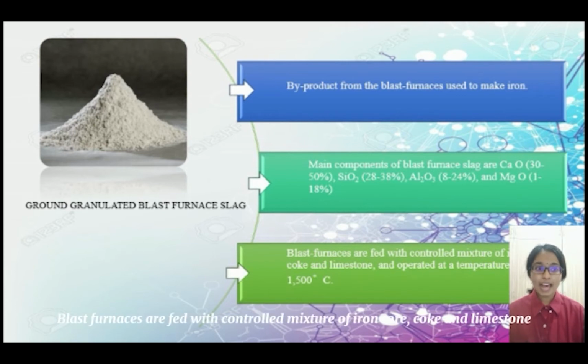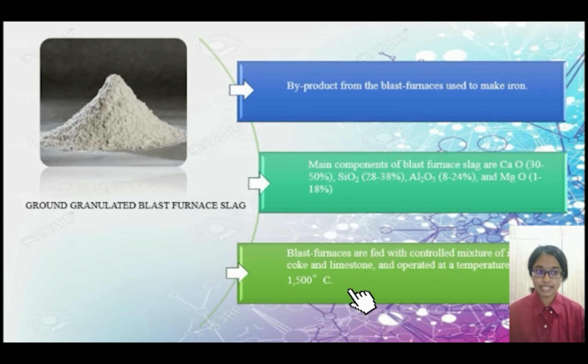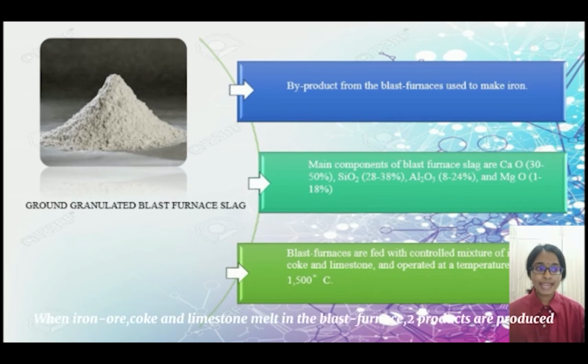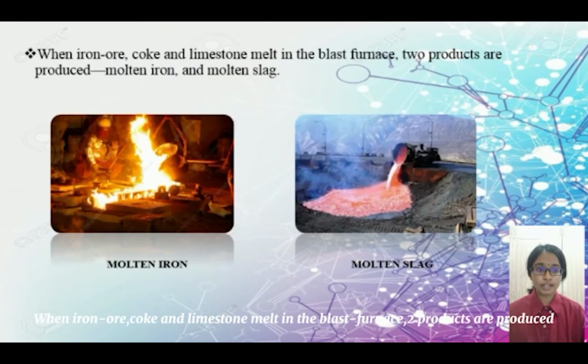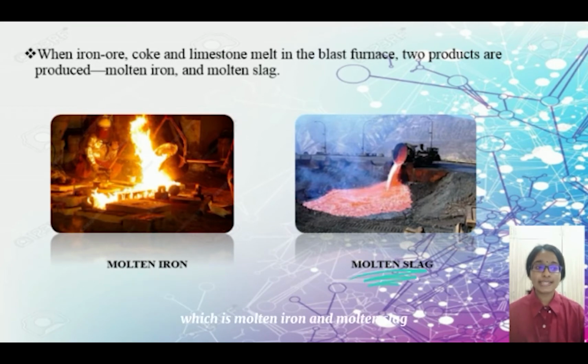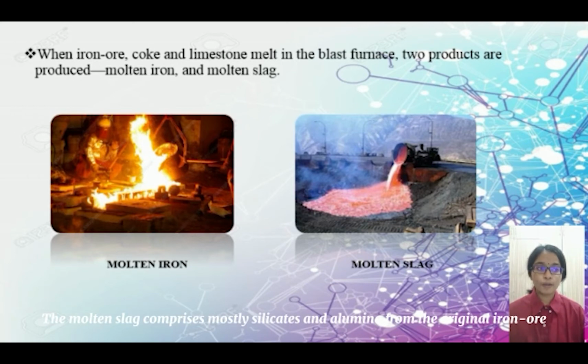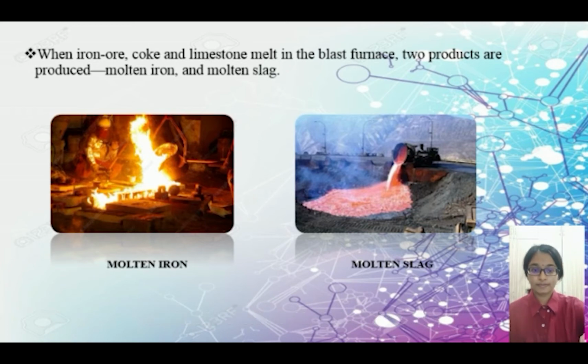Blast furnaces are fed with a controlled mixture of iron ore, coke and limestone and operated at a temperature of about 1500 Celsius. When iron ore, coke and limestone melt in the blast furnace, two products are produced, which are molten iron and molten slag. The molten slag is slightly lighter and floats on top of the molten iron. The molten slag comprises mostly silicates and alumina from the original iron ore combined with some oxides from the limestone.